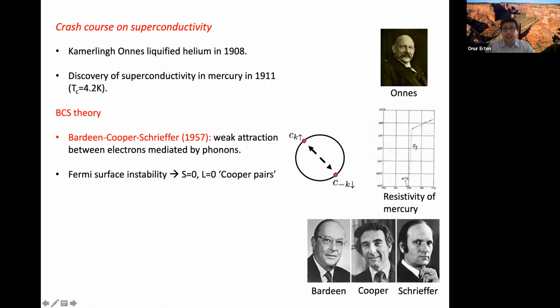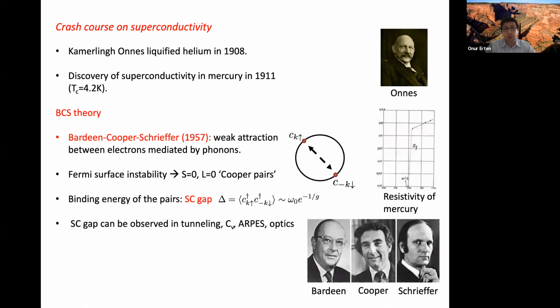And one characteristic property of superconductors is the superconducting gap, which is effectively the binding energy of these pairs. In the case of BCS theory, this is proportional to your transition temperature. And this is one of the most characteristic properties of the superconductor because it can be seen experimentally in various techniques such as tunneling, specific heat, angle-resolved photoemission spectroscopy, or other optical techniques.